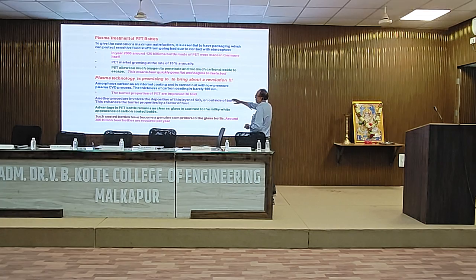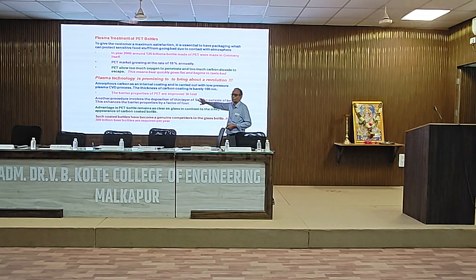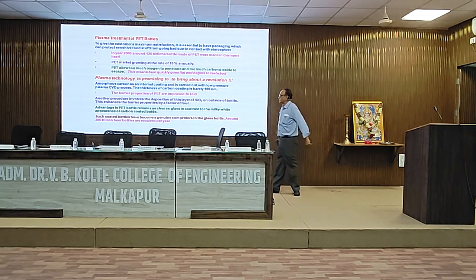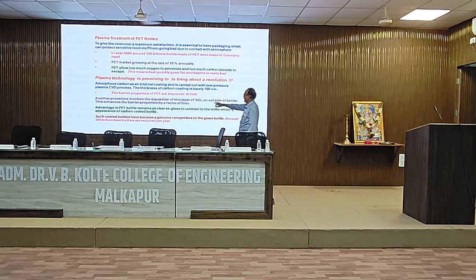Thickness of the carbon coating is barely 100 nanometers, 100 into 10 to the minus 9 meters. And the barrier properties are improved by 30 folds by such a small thin coating. Another procedure involves a layer of SiO2 that is formed on the outside of these bottles, and this enhances the barrier properties by a factor of 4. These are from the data again.